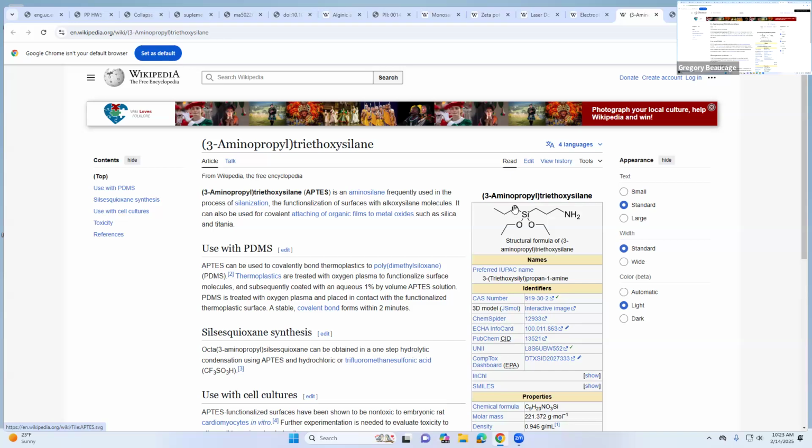So those will hydrolyze with the OHs on the surface and make an SiO-Si bond. The ethanol flies off. That's a byproduct. It's a condensation reaction that condenses ethanol, right? So that'll make like a tripod. Silica is actually just like carbon. It's a tripod with a flagpole. But on the flagpole, the flag he's flying is a cation, an amine group, right? So that's like your standard cation thing.